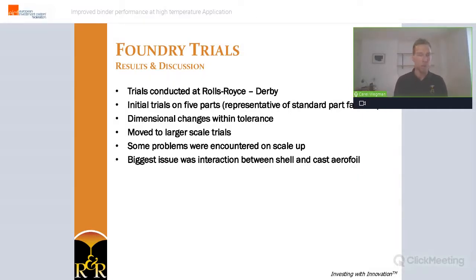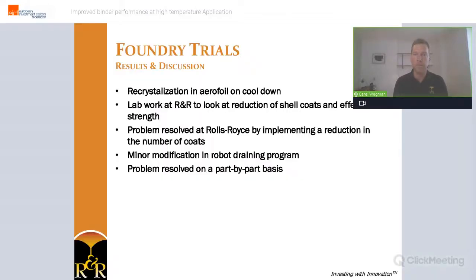Trials were followed up by a rollout of the binder across the complete product portfolio in this plant. But during this scaled-up trial, issues were raised with an interaction between the shell and the cast aerofoil. On the longer blades, recrystallization was seen in the aerofoil due to stretching of the blade on cooldown. So while the dimensional issues were resolved, another major issue had to be addressed.